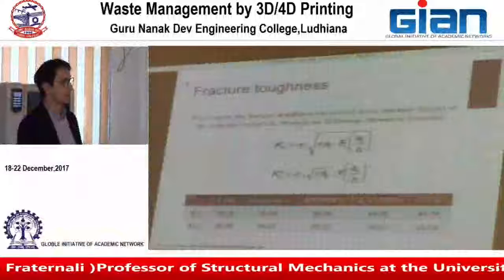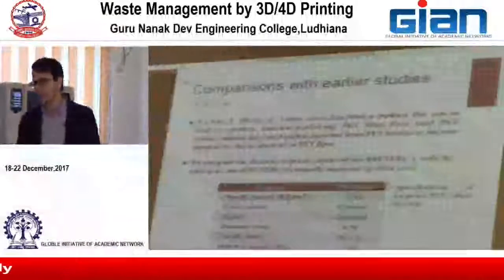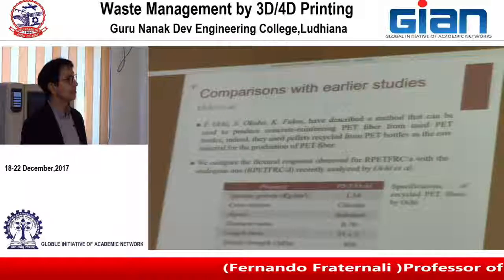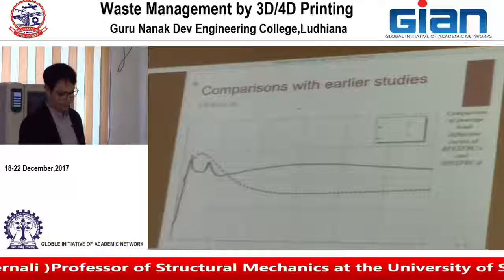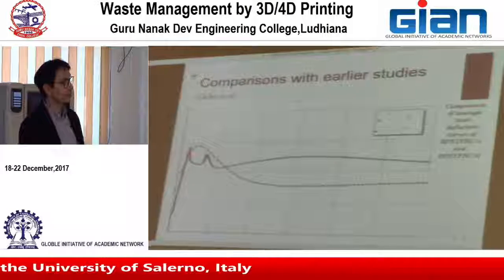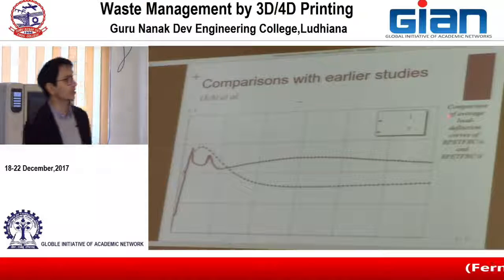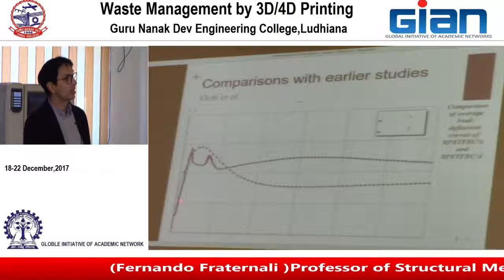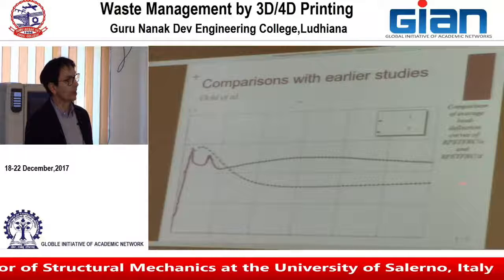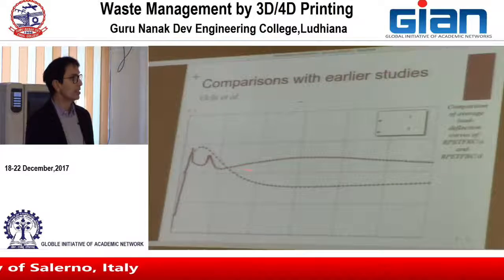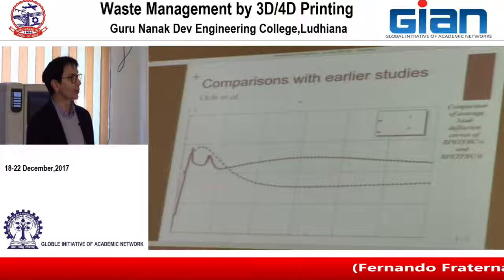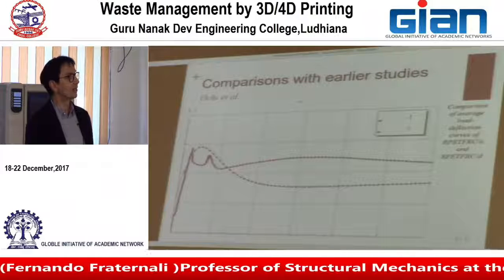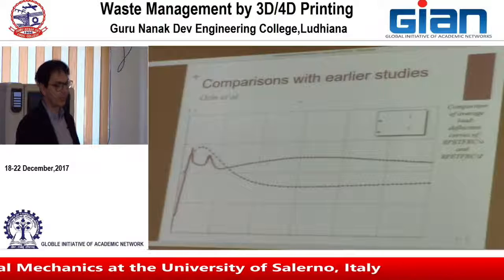And we also performed some comparisons with earlier studies on the use of recycled PET fibers, some available literature studies by some Japanese researchers who first examined this kind of reinforcement of concrete, and our results were more or less comparable to the ones in the literature. Those are the comparisons. Unfortunately, the legend is not visible. This is our curve, and this is the curve obtained by the Japanese researchers. So we obtained a result that is somewhat comparable in the first cracking regime. It is different in the highly damaged regime.